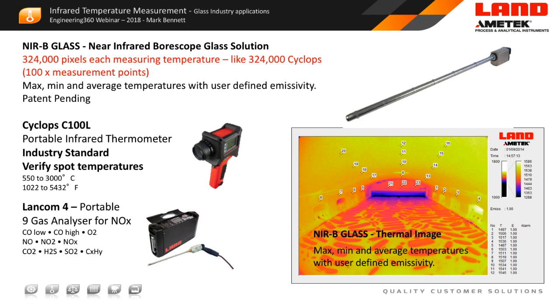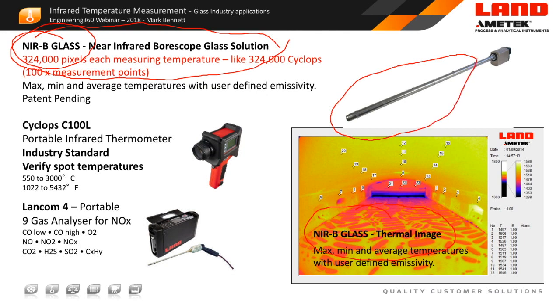The optical profile, as we've discussed in the previous slide, is monitored by taking several point measurements along the walls of the tank to look at the shape of the optical profile. Now, to take an optical profile using a Cyclops unit can take several hours. However, what you can see here is we have the NIRB glass true thermal imager for monitoring temperatures within the glass tank. So this is using a thermal imaging device which looks along a lens system here, such that the actual thermometer, the detector, the important part, can be stabilized outside the glass tank to give accurate and stable measurements continuously inside the glass tank.